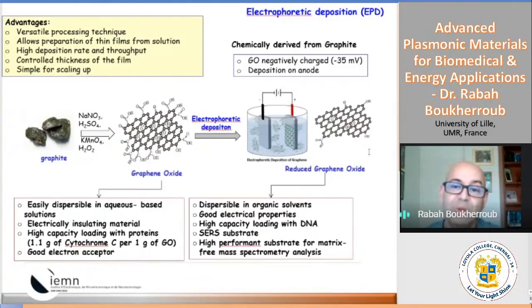So what we wanted to do was check if we can use what we call electrophoretic deposition, and this is a process applied in industry, and it works very nicely on a large scale. You can use it in square meters, depending, of course, on the instrument you have. And the concept is so simple. You have two electrodes, you apply your potential. In the electrolyte or the medium, you have something which is charged. Graphene oxide is negatively charged, but you can make it positively charged if you mix it with metal ions, for instance.